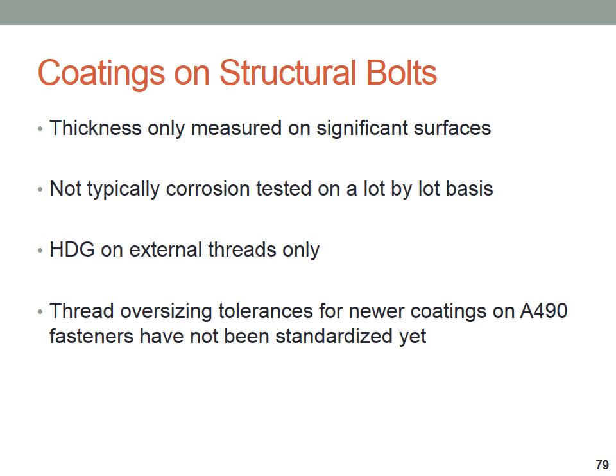Typically that's not a huge problem, but one of the reasons this doesn't happen is some of these salt spray tests can take 14 days or longer. There's oftentimes only 14 days of delivery available between when an order is placed and when it needs to be in a connection. And so for the most part, those tests are done on a production level basis, not on a lot-by-lot basis. Hot dip galvanizing is on external threads only. The internal threads of a nut are actually tapped after coating, and you basically have bare exposed metal on the internal threads of a nut when parts are hot dip galvanized.